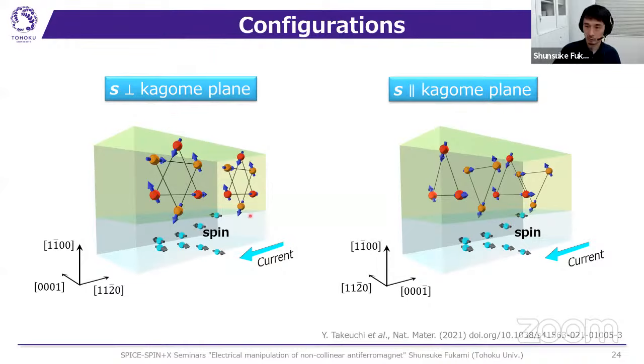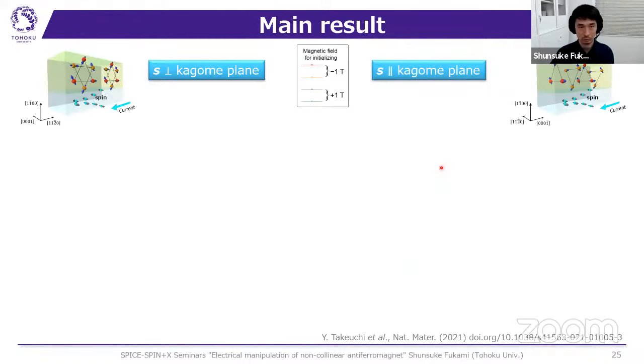Okay, and we studied two configurations. This is the first configuration, in which the Kagome plane is expected to be perpendicular to the accumulated spin, whereas this shows the second configuration, in which the accumulated spin is in the Kagome planes. We compare the results observed in these two configurations. Okay, so let me show the main results.